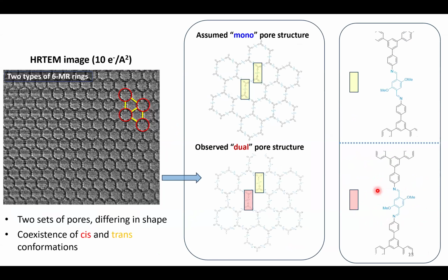Now we have the low-dose imaging capability, so we can take a look at the structure using TEM. Interestingly, we found that this material actually contains two types of 6-membered pores, but none of them has the regular hexagonal shape. Specifically, one type consists of 6 convex edges, giving it overall a nearly round appearance. The other combines 3 straight edges with 3 concave edges, resulting in shrunk pores with smaller pore size. And this is radically different from what people previously believed.